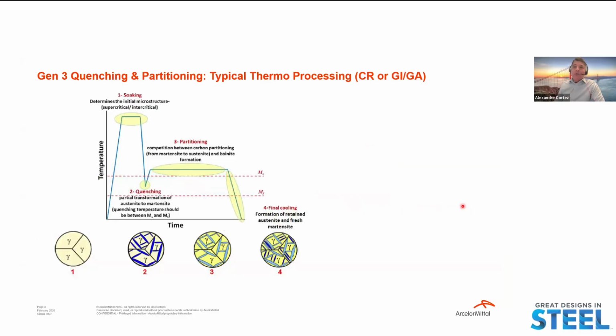Okay, so next I will briefly explain the Q&P concept behind the Gen 3 microstructure. Gen 3 commonly uses the quenching and partitioning process. This is a typical thermal processing that includes 4 phases. The first one is soaking, which determines the initial microstructure. Basically, we have austenite grains formed during soaking. And then we have the second phase, quenching. This is a partial transformation of austenite to martensite. And in this phase, we have martensite laths formed during quench.